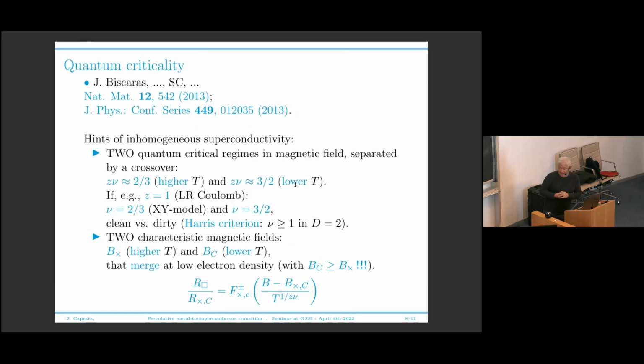Quantum criticality is, again, something that at that time we published a paper in Nature Materials about this behavior, which was at the time very, very intriguing. It seems that you have two quantum critical regimes in the system. Now, you take the interface and you drive your metal to superconductor to metal transition by means of a magnetic field.